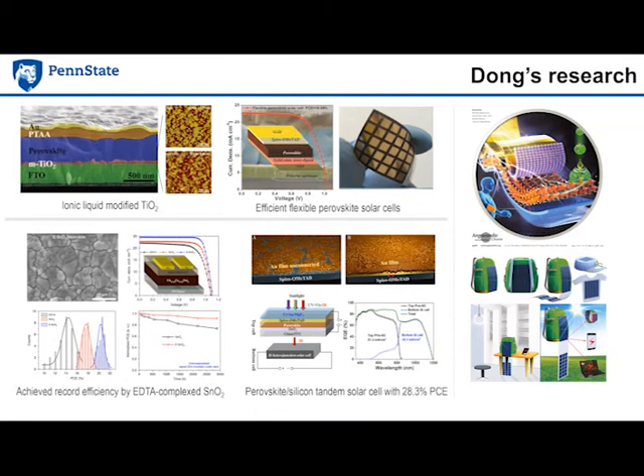They can last over 3,000 hours, which still remains over 90% of the initial power conversion efficiency. And another recent work of Dong's is these tandem solar cells. He used a very technical method to realize this uniformly distributed film, and it is very thin and transparent. So later on, he is able to make this semi-transparent top cell, as shown here.